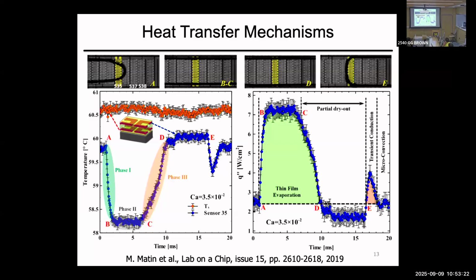So let's look at this, let's address some of the things. Obviously, there are a series of papers that I will be happy to discuss with you. Let's look at sensor 35, where the tip of the elongated bubble moves over the surface. This shows the temperature. Remember, I was telling you that the temperature at the interface of the silicon and the polymer layer always stays constant. What drops is really the surface temperature. So again, when the elongated bubble moves over the surface, you see rapid cooling of the surface, and then we stay that way.